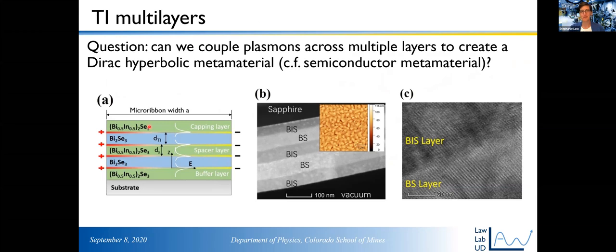The other thing that we worry about on that note is whether or not the two surface states have the same carrier density. Because if you have any band bending at the top surface or the bottom surface, one might have a different carrier density than the other. And so again, that's part of why we've started doing this bismuth indium selenide encapsulation, to make sure that if there's band bending, it's at least symmetric on both sides, to try to make these surface states as similar as possible.